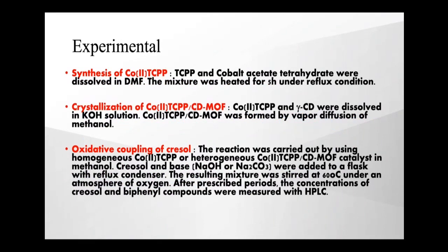This slide shows the experimental procedures. For the synthesis of cobalt TCPP, TCPP and cobalt acetate tetrahydrate were dissolved in DMF. The mixture was heated for 5 hours under reflux condition. For the crystallization of cobalt TCPP CDMOF, cobalt TCPP CDMOF was formed by vapor diffusion of methanol to the feedstock solution including cobalt TCPP. Oxidative coupling of creosol was carried out by using homogeneous cobalt TCPP or heterogeneous cobalt TCPP CDMOF catalyst in methanol.